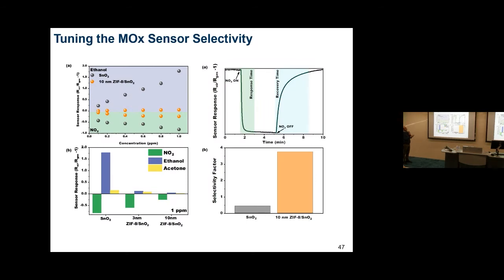You can see various curves here, but the most important is this graph. If you look at pure tin oxide, it responds to NO2, ethanol, and acetone. Now, when you start increasing the ZIF-8, you can basically cut off ethanol and acetone and just maintain the response to NO2. This may also be good for hydrogen because it's quite small.